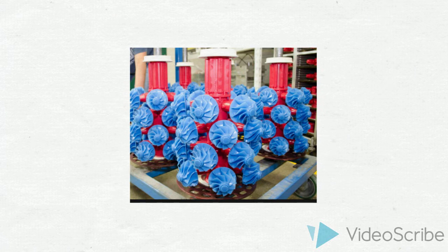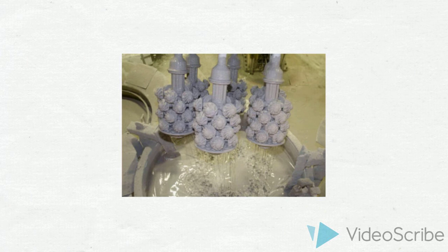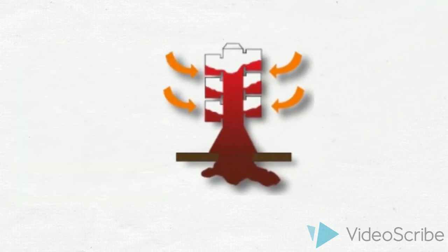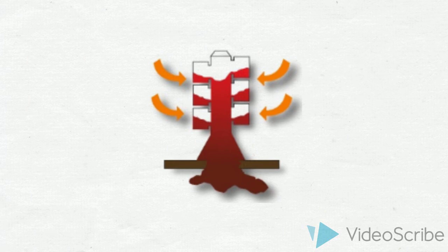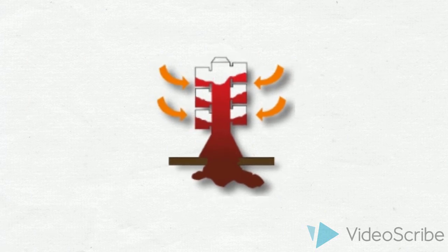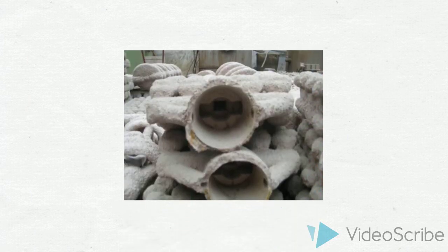a mold. Once the wax assembly is complete, it's dipped into ceramic slurry, drained, coated with ceramic stucco, and dried. This step is repeated several times depending upon how much metal the mold needs to hold downstream in the process. After the ceramic layering is completed, all wax, both pattern and sprue, is melted out of the ceramic shell. This empty ceramic shell will in turn receive the molten metal.